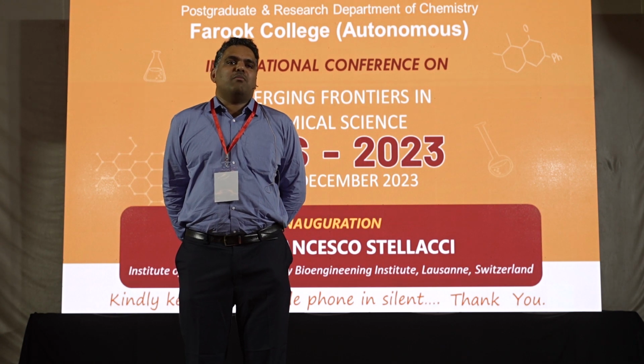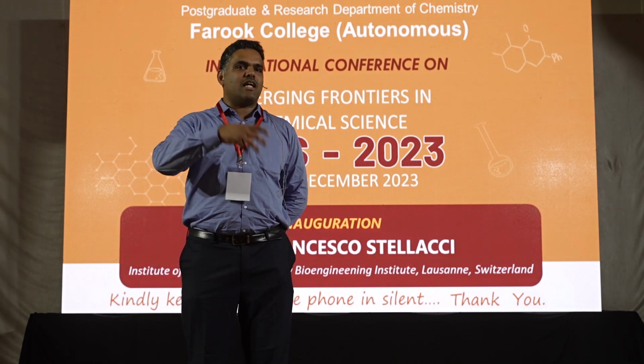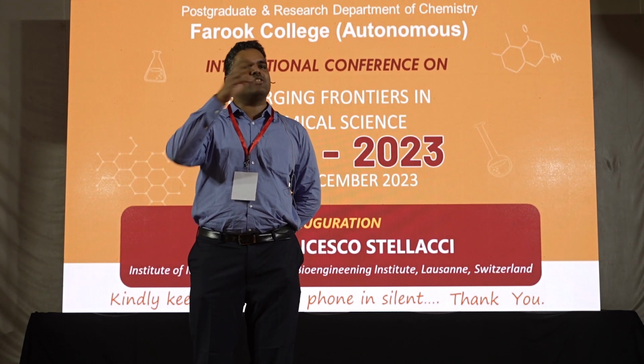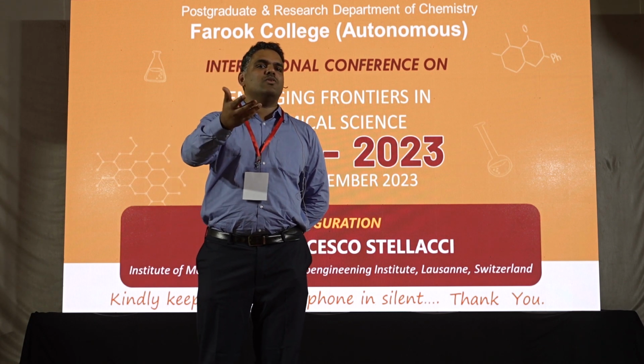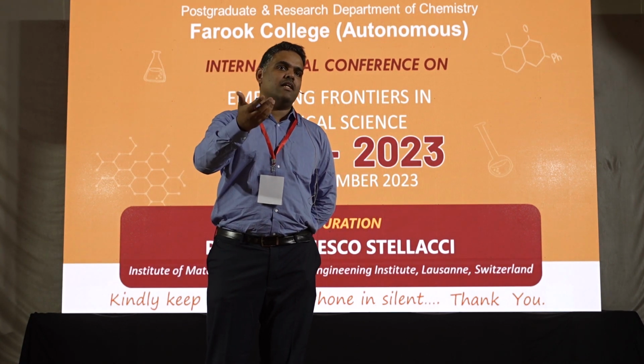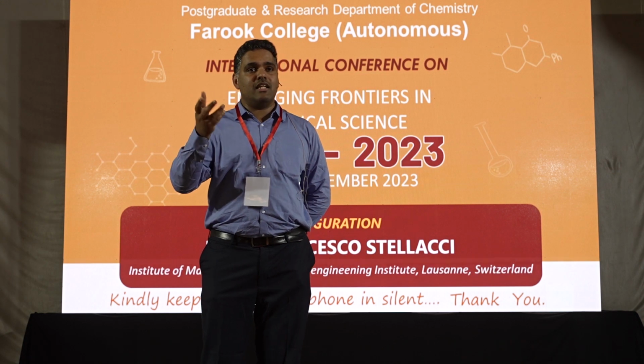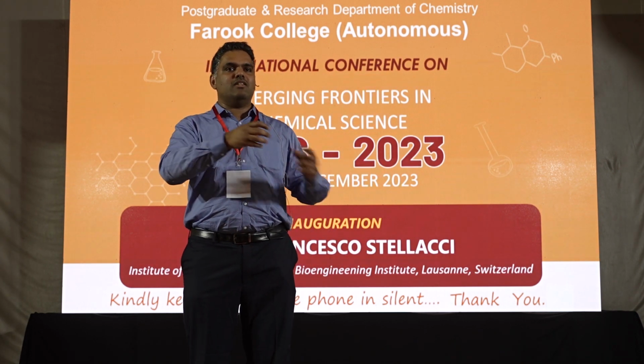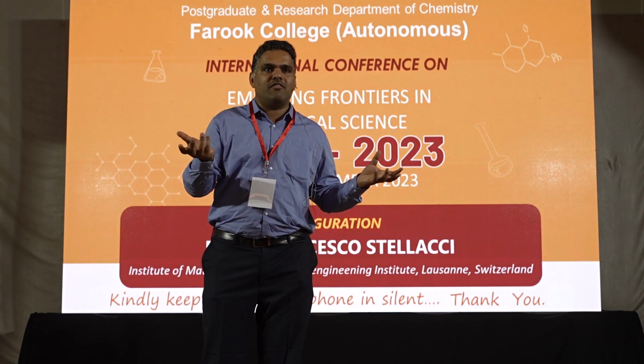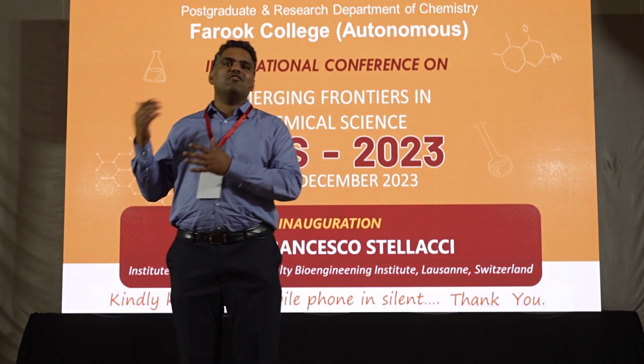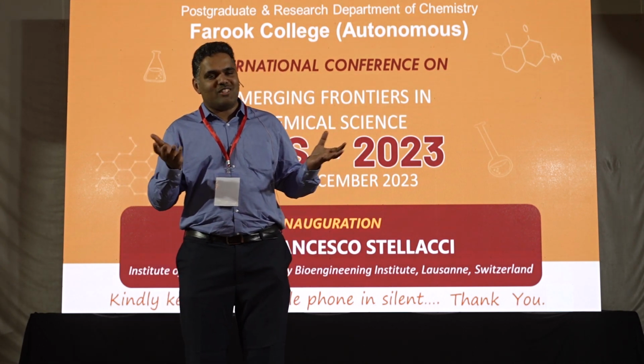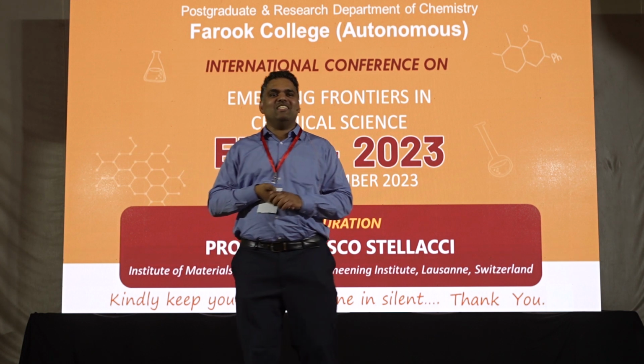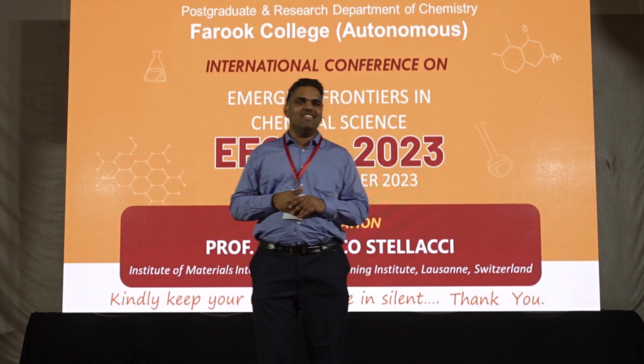What can happen at maximum is, if the temperature is high, if you put laser light on it in oxygen, it can get oxidized into graphene oxide. In the worst case, it can generate carbon dioxide by making some defect in graphene. But if you are very unfortunate, maybe it can also form carbon monoxide, and that's very, very unlikely. Okay, thank you.